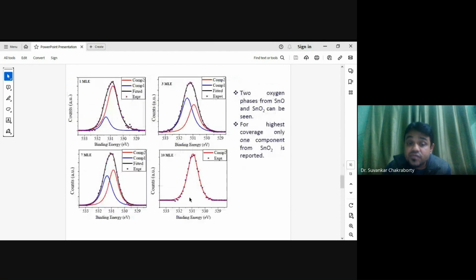Okay. Now, if we go to the oxygen fitting also, at lower thickness, we can see 2 oxygen components, one from SnO and another from SnO2. But when you go to the highest coverage, that is 10 monolayer, we can see only one, and it is mainly due to the SnO2, because SnO is buried under the SnO2, and XPS cannot go up to that thickness.